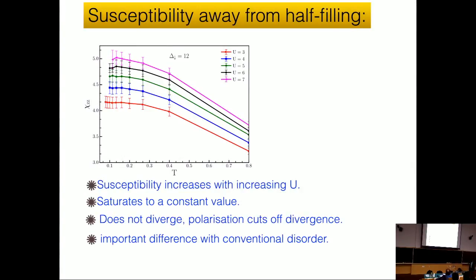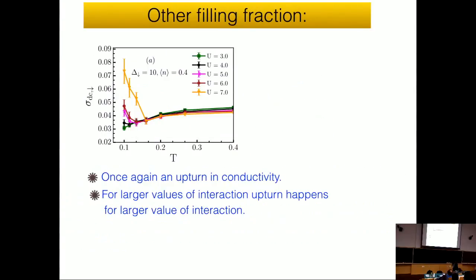If you remember the Finkelstein flow equations that I had written down, it could very well be that associated with this susceptibility there is an interaction strength, and instead of that interaction strength running away, because of the way we put in disorder, this forces the interaction strength to saturate to a finite value. This could then lead to a metal-insulator transition that could possibly be explained in a Finkelstein-Belitz-Kirkpatrick sort of field theory.